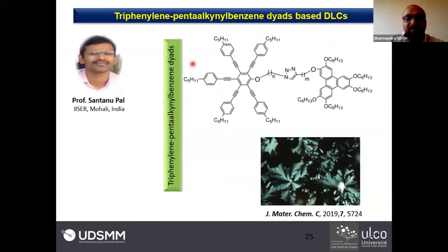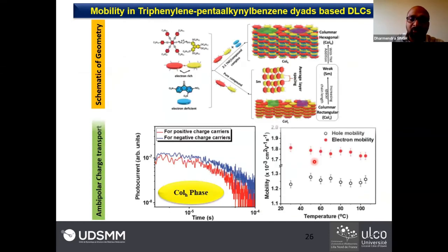Later on, we also studied one more compound prepared by Professor Santanu Pal at IISER Mohali, where he has attached triphenylene-pentaalkynylbenzene dyads in addition to the triphenylene core. We found that it is also a very good compound which exhibits ambipolar charge transport, in which electron mobility is slightly higher as compared to the hole mobility. And one important thing we have observed here: when the size of the molecule is heavy, it always shows a dispersive nature in the photocurrent curve. This compound was very interesting for organic light emitting diodes, and we also fabricated organic light emitting diodes using these molecules. But unfortunately, I have not shown it here.